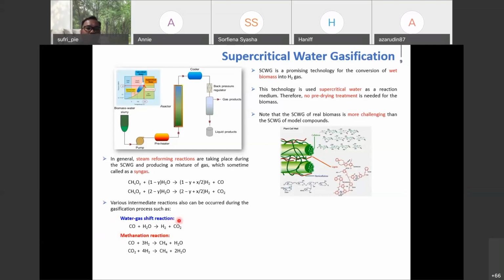So whether we want to turn this reaction on or turn that reaction off, we should do it with the catalyst. The catalyst will activate the water gas shift reaction, so we can have a higher amount of hydrogen. So hopefully the catalyst that we design and test will be active for this reaction, so it can boost up the yield of hydrogen. These two reactions will control the final product. Either the final product is syngas rich in hydrogen, or the final product is syngas rich in methane. So we have to control the properties of the catalyst.